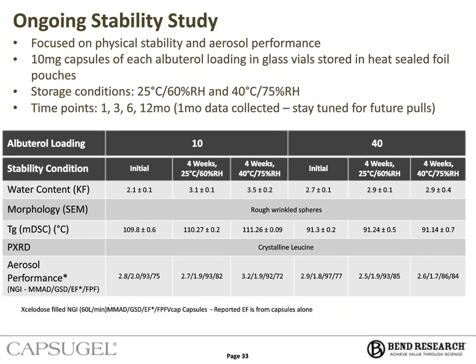So again, we see the different tests that we discussed, so the water content and a little bit of movement seen there, presumably due to a little different equilibration profiles between the powder and capsule. These can easily be mitigated through desiccant selection. Morphology and the glass transition temperature, PXRD results all remain similar, and we're still seeing acceptable aerosol performance. So I guess the takeaway there is stay tuned for future data.